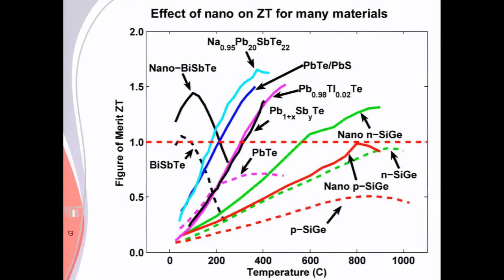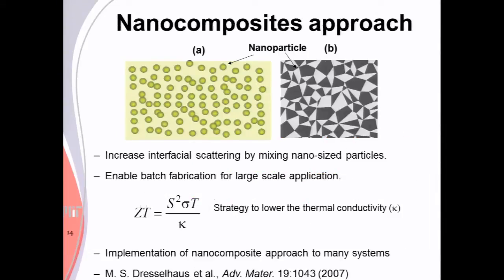So one thing is to try many different materials, and you could see, well, in 1990 we didn't have all these materials. We had lead telluride, and we had bismuth telluride. We didn't have too many other things. And now we have a very large assortment, and we have them in bulk form and different nanostructures and whatnot. And all of that is helping. At that time, we proposed two things. One, the nano route, and the other is a new materials route. Both of those have actually yielded very good results, and we benefited from both approaches.